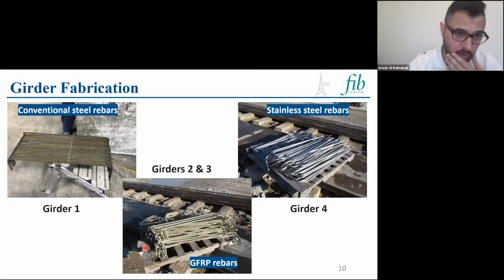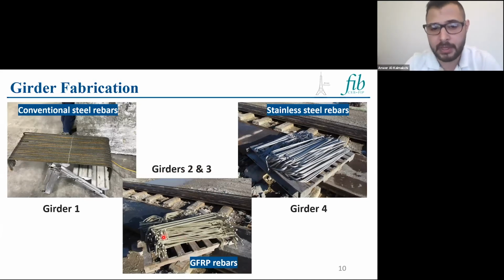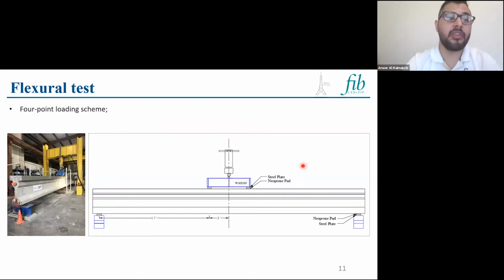Here is a picture of the shear reinforcement. This is girder 1. We can see those carbon steel rebars. There is some rust. For girders 2 and 3, we used GFRP, which is corrosion free, and for girder 4, we used stainless steel rebars. For the flexural test, we tested our girders in a 4-point loading scheme. The test was done at the Florida Department of Transportation Structures Research Lab in Tallahassee, Florida.